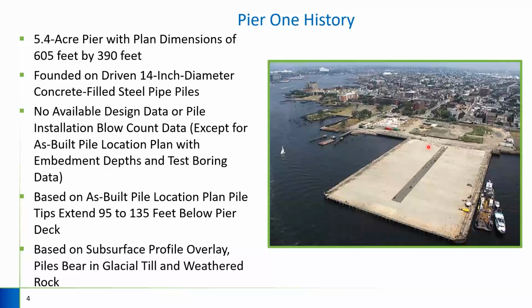Additionally, during our preliminary design, we also drilled 8 borings around the exterior of the structure, including 3 on each long side and 2 on the short side, to help us confirm the previous installation data. Based upon the as-built pile location plan, we were looking at pile tips between about 95 and 135 feet below the pier deck.